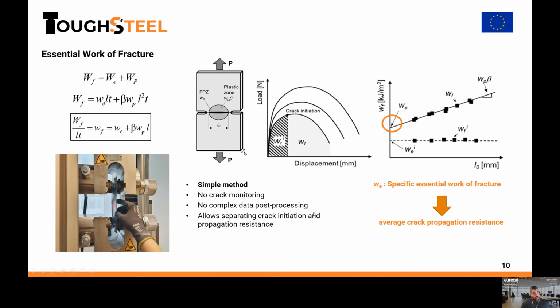Also, an interesting part of this essential work of fracture is that it allows separating the contribution from initiation and propagation resistance. As I said, this specific essential work of fracture is an average, so it contains initiation and propagation, but we can also measure essential work of fracture or fracture toughness at crack initiation by integrating the area only up to the point of the crack initiation. In this case, it could be detected, for example, with a DCPD system or similar. When we evaluate this fracture energy, contrary to the total work of fracture, this work of fracture at initiation is quite independent of the ligament length.